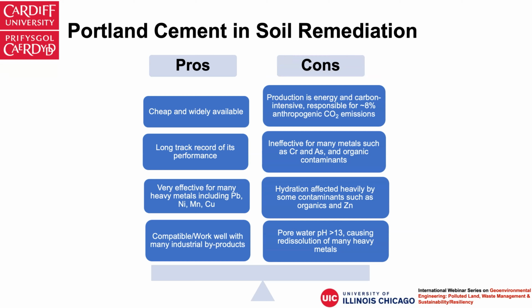Also, most organics, as well as zinc, will affect the hydration process of Portland cement very much. Therefore, if you have high concentrations of organics or zinc, the Portland cement hydration will be significantly retarded. And last but not least, the pore water pH of Portland cement is extremely high. That is because one of the main hydration products is calcium hydroxide. The equilibrium pH of that product is around 12.5, plus other alkaline materials like sodium and potassium. The pore water pH is usually above 13. That high pH will cause the redissolution of many heavy metals within soil. Later we'll see a graph of this.